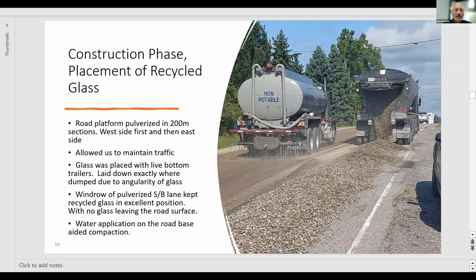So the road was pulverized in 200-meter sections, did the west side first, then the east, and that allowed us to maintain traffic. As the glass was placed, it laid down exactly where it was dumped due to the angularity of the glass. The windrow of the pulverized southbound lane kept the recycled glass in excellent position, with no glass leaving the road surface. That was a high priority for us. You can see also water application on the road that aided in compaction.